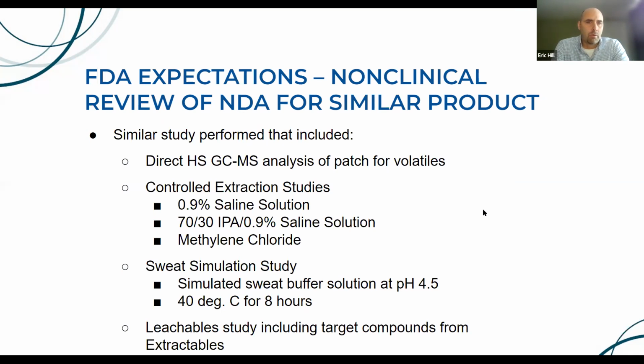They also directed controlled extractable studies using a 0.9% saline solution, 70-30 IPA, 0.9% saline solution, as well as methylene chloride. They also directed specifically that a sweat simulation study be done. And they directed that the simulated sweat be a buffer solution at pH 4.5, and also that it be done at 40 degrees C for 8 hours. Now, the 40 degrees C, as I mentioned before, mimics use conditions under exercise. And the 8 hours was directed because the maximum use time for this patch in particular was 8 hours. And then they directed that the leachable study be performed, including the target compounds from the extractables work.